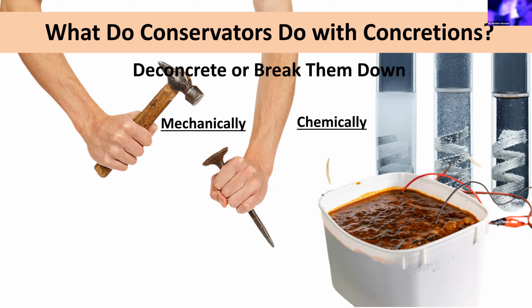However, a lot of these methods were very uncontrolled and the outcomes were very unpredictable and came with a great risk for the artifact. Obviously, chiseling, you can get very good at it. I do know people that are very, very good at it and have a lot of finesse in being able to chisel out artifacts from a concretion. But on average, your average conservator, that's a lot of skill and a lot of precision you need. And sometimes it's unpredictable what you're going to get in terms of cracks. So you can actually break your artifact. With electrolysis, you can accidentally explode your artifact from the inside out if you use too high settings.